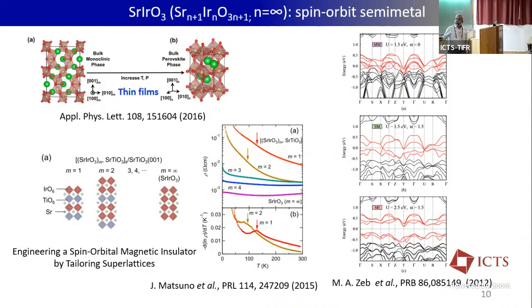Otherwise, the bulk phase always goes to this monoclinic phase, which does not show many interesting properties. But you can grow this by following the epitaxy method, and you can grow this perovskite phase, and this perovskite phase is supposed to give rise to various topological phases.